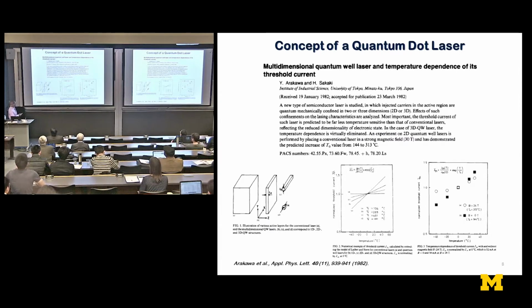Now, in 1982, Yasu Arakawa and his mentor Hiro Sakaki did a very clever measurement, and they reported this measurement. First, they calculated theoretically what the temperature dependence of a threshold current would be for a normal bulk, or as we call it a three-dimensional gain media laser, for a quantum well laser, a quantum wire laser, and a quantum box laser. So you see these four. In the bulk laser, the threshold current goes all over the place with temperature, and that's not good. And in a quantum dot laser, you can see there is no temperature dependence. The characteristic temperature, as we call it, is infinity.